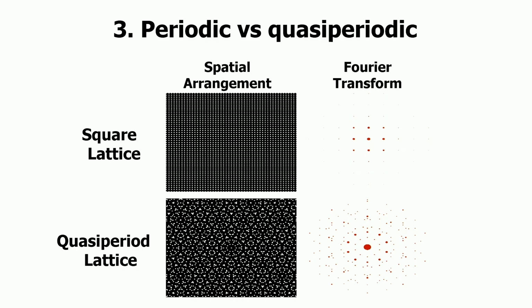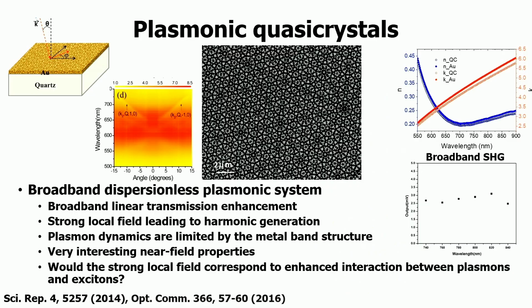Just to understand the concept, if you arrange an array of these scattering elements in a periodic, square lattice and look at the Fourier transform, the dispersion profile is basically a square lattice. However, with the same density, the same number of scattering elements, if they are arranged in a quasi-periodic lattice with five-fold rotation symmetry, the dispersion profile in K-space is pretty dense, right? This means that for given K values you can have different orientations as well. So it'll have different Ks, that means different lambdas, different launch angles and orientations for which this will work.